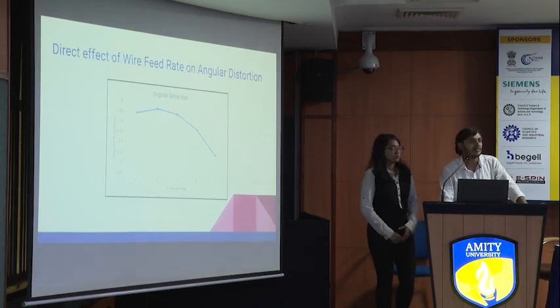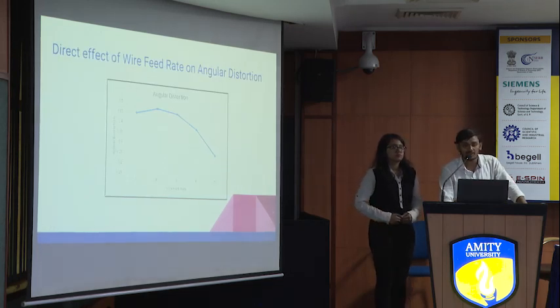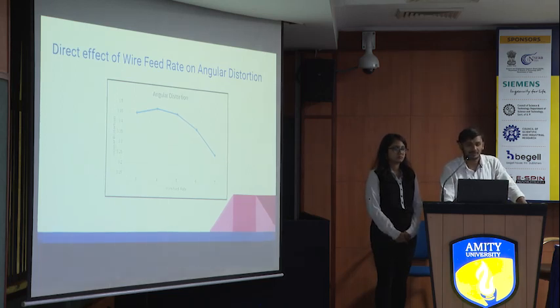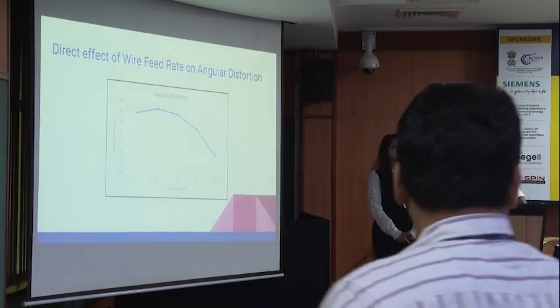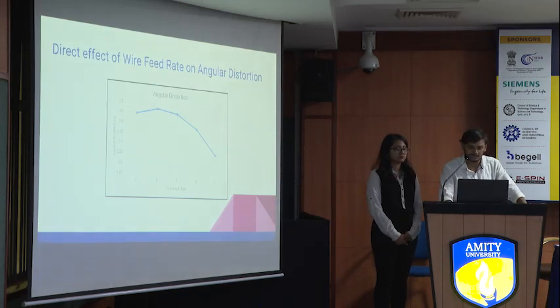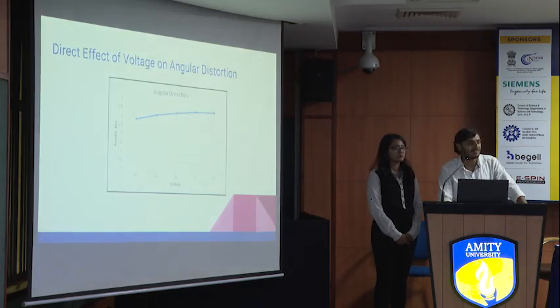And after the results, we plotted the graph to check the significance of these results. So from the graph, it is pretty clear that by increasing the wire feed rate, the angular distortion decreases, which is in our favor. And by increasing the voltage, the angular distortion is also increasing. The reason is quite clear, because if the voltage increases, the heat gradient also increases, and by more heat gradient, the angular distortion automatically increases.